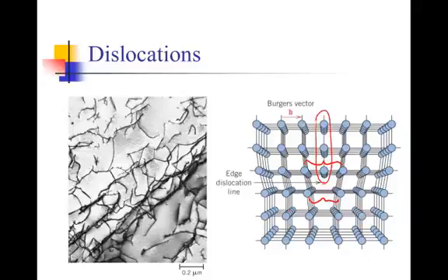And so this is called a dislocation, and it makes it easier for the crystal to be deformed under mechanical stress. If you think of pushing here and pushing here with shear mechanical stress and trying to shift one plane of atoms over on top of the other, to do that, you have to temporarily break the bonds and force an entire area of all the atoms in this surface past all the atoms in the surface below it.